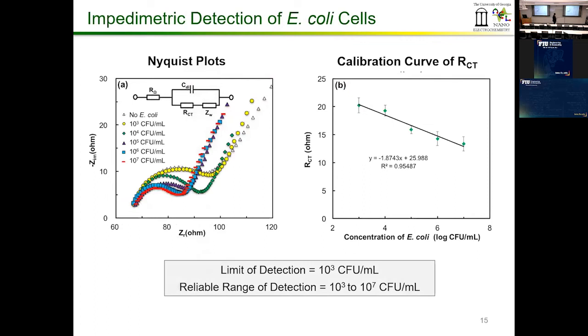So this is a typical impedance response curve. We call it Nyquist plot. You can see when there is no bacteria present, and then when you have bacteria present at different concentrations, you can see the change in impedance. When you actually take the magnitude of this semicircle, which is the charge transfer resistance here, that would be approximately equal to the diameter of the semicircle, then you can see that is plotted here versus the concentration of